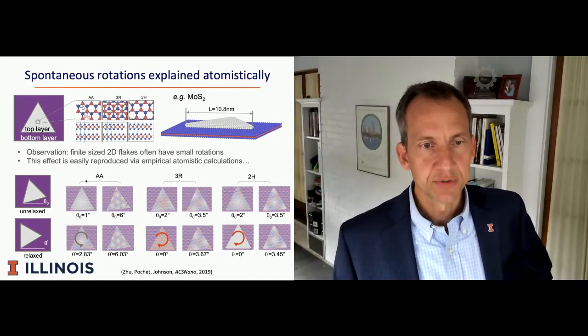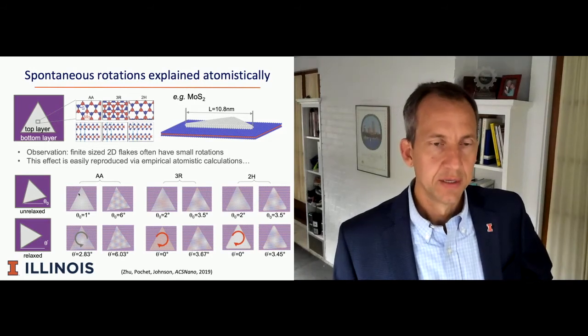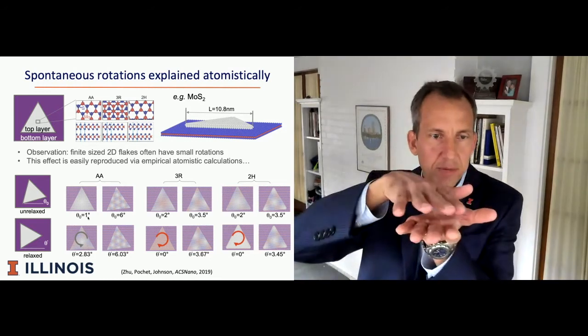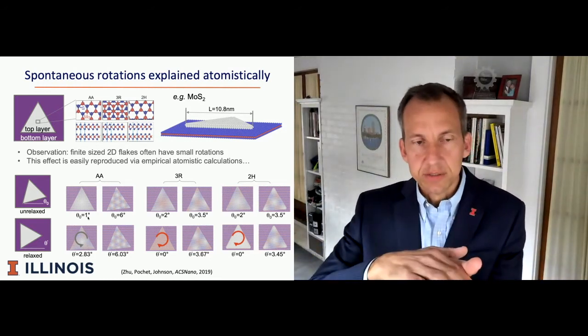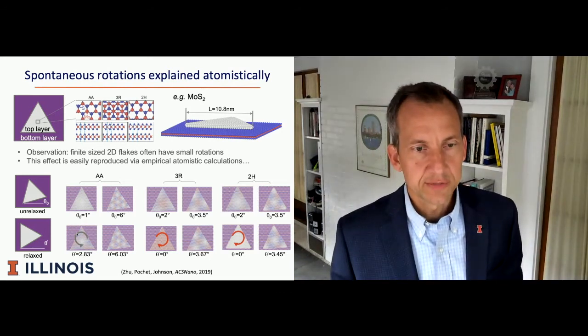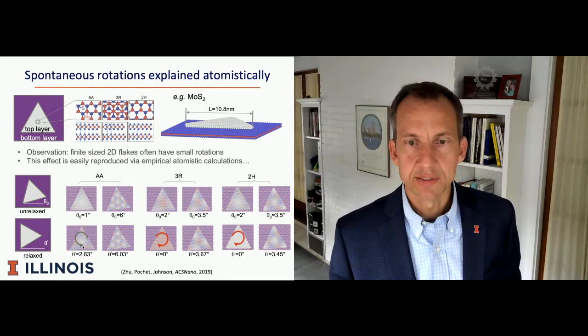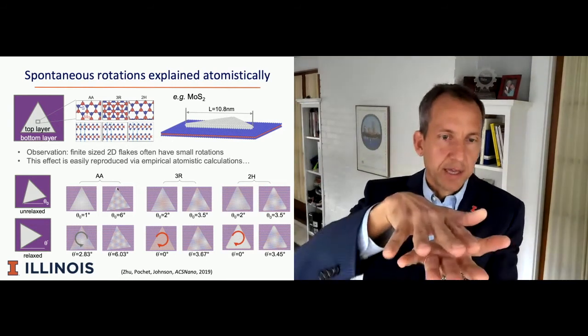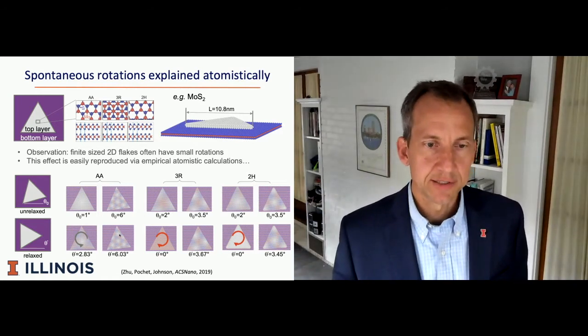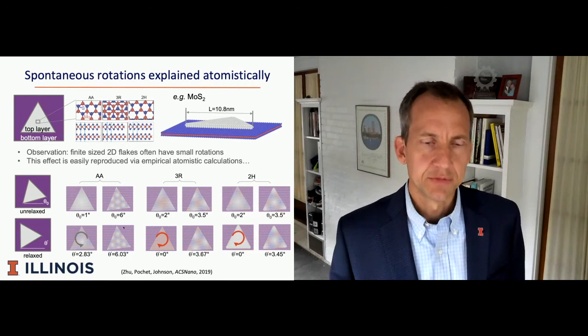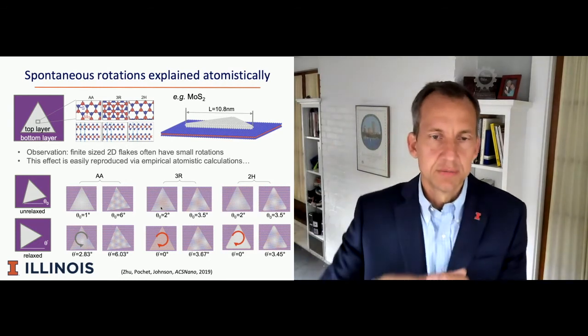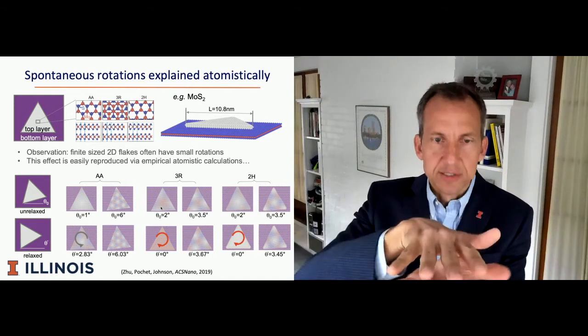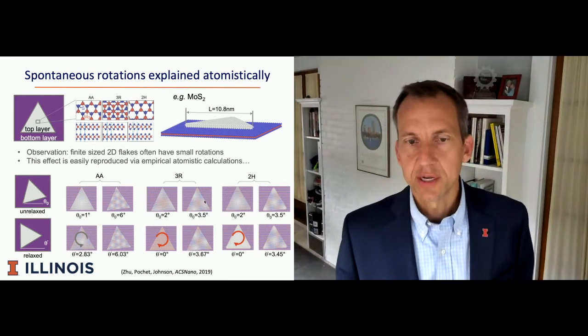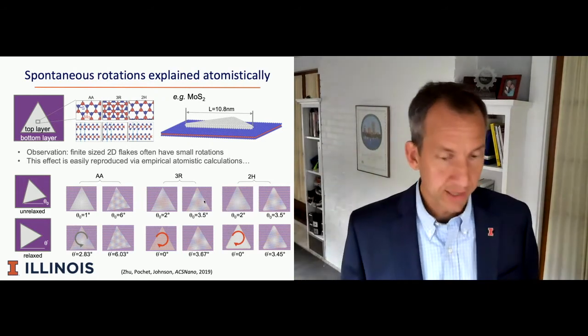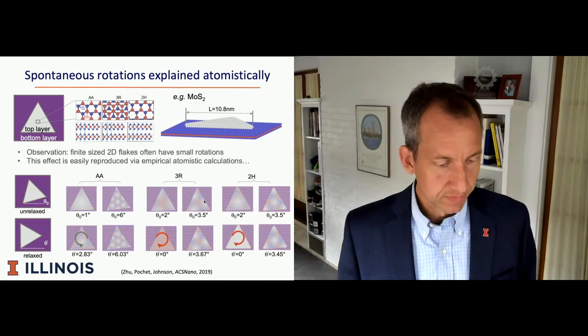We started, for example, from AA stacking, which is shown above. If we initially rotate the triangle by 1 degree and then minimize its energy, we find that it rotates further in the same direction and it goes to 2.8 degrees. On the other hand, if we start with an AA stacking at 6 degrees and allow it to relax, it hardly rotates at all, just a tiny amount. If we look at the 3R stacking, for example, and we start with a 2 degree rotation and we allow it to relax, it rotates back to 0 degrees orientation. Whereas if we start at 3.5 degrees and then allow it to relax, it barely moves at all.